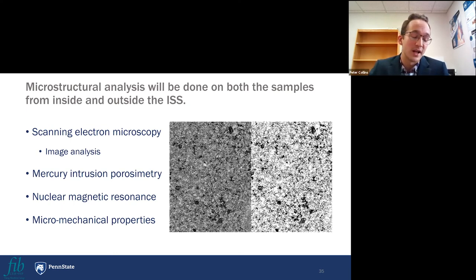So we also plan to do mercury intrusion porosimetry. That gives us a nice idea of the pore structure and density of the materials and how gravity influences that. This will be more so for the samples that were a part of the experiment we plan to do inside the burst pouches, as well as nuclear magnetic resonance. This is a good way to understand the differences in bonding of the alumina silicate chains that have formed in the geopolymer. And so we'll do some of that studying on both the samples inside the ISS and outside the ISS to see what influence gravity has, as well as the extreme environment has, on the network of the polymer.